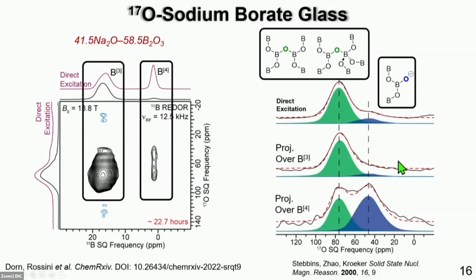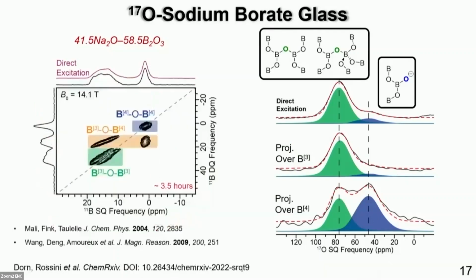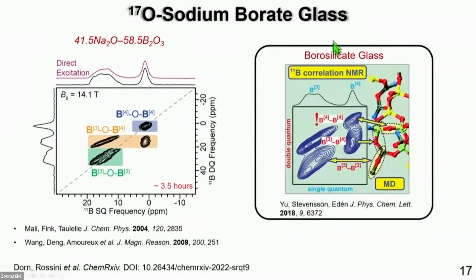Now, this is intriguing because one would not expect that a BO4 unit would have a non-bridging oxygen, because then the formal net charge would be -2. So to further investigate this, we recorded a 2D boron-boron double quantum, single quantum homonuclear correlation spectrum. And what we see is that there are very intense BO4 correlations, suggesting that this motif must be abundant within this glass. And I want to point out that very similar abundant motifs were observed in this borosilicate glass from Matthias Eden's group in 2018.